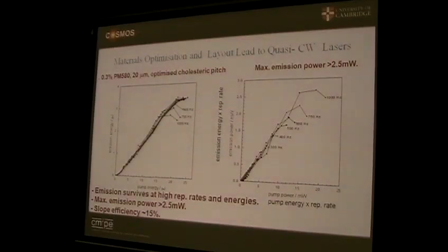We haven't needed to go further because we're in a university research department, but there's no reason why those lasers should decay. If they don't saturate at the top, then you're not bleaching the dye, you're not reorienting the dye, then it'll work in that regime, and the cell's sealed. So we can laser continuously for months, put it down, pick it back up, and you get the same output.